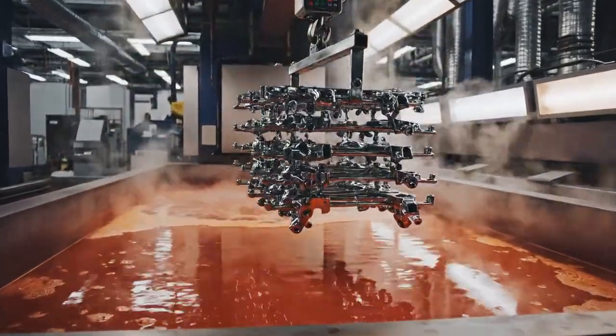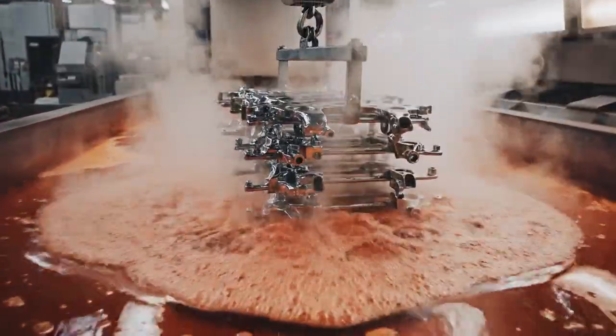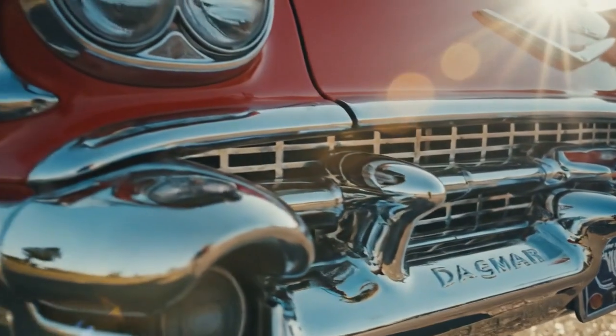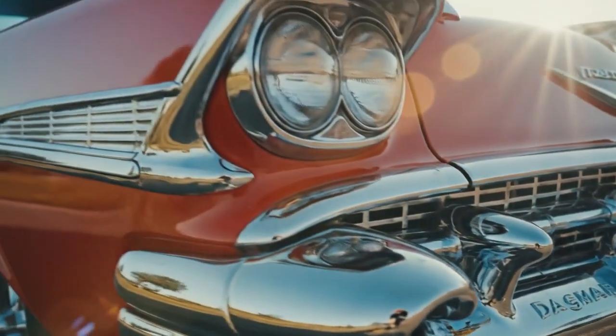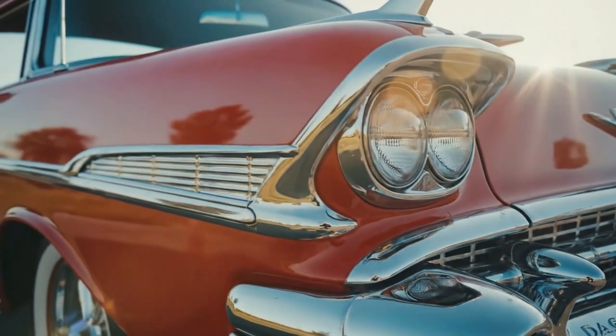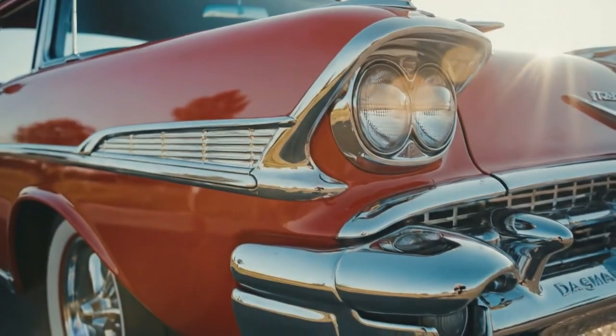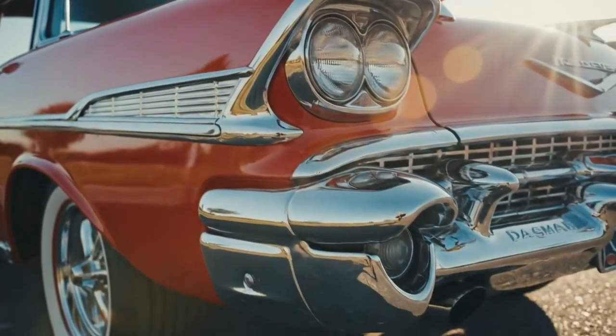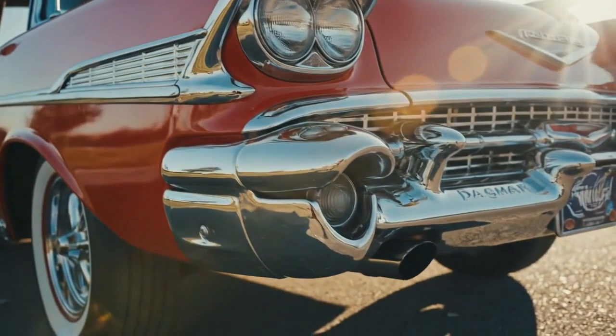Third, the chrome layer was applied from a bath of chromic acid, hexavalent chromium, CrVI. This top coat provided extreme surface hardness, a characteristic blue-white color, and a surface so dense that atmospheric moisture, road chemicals, and UV radiation had limited ability to penetrate it or initiate corrosion. Original American cars from the 1950s and early 1960s, chromed correctly using this process, had bumpers and exterior trim that remained visually correct for 20 to 30 years of regular outdoor exposure without replating. This was not just an aesthetic quality.